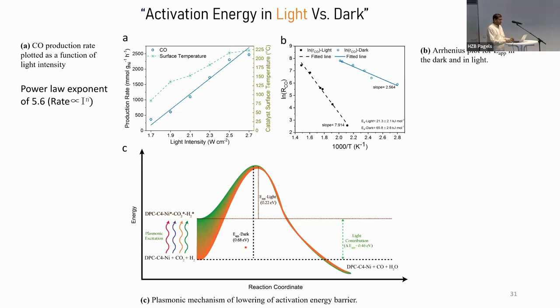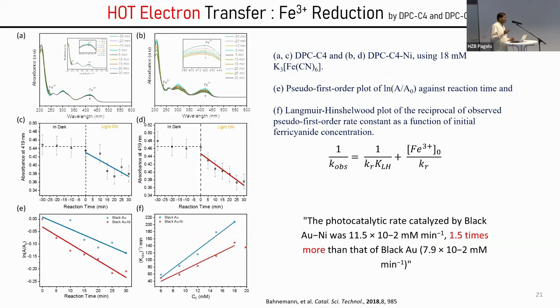So this hot electron versus thermal is still a debatable concept, still difficult to convince some of the time, especially your referee. So we carried out a range of other reactions to prove this. One of these is to prove that the black gold nickel can transfer the electron. It's a very basic question that we asked, and we carried out this Fe3+ to Fe2+ reaction, and this can only be done by electron transfer. It cannot be done by the heat, right?